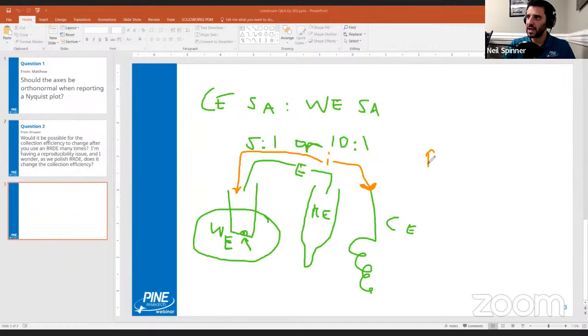So typically that's platinum, it's graphite. Sometimes if you're doing other kinds of systems, it'll be like a mesh, some people have like a nickel mesh or things like this, but basically just something that is a big surface area, large. The exact shape and size doesn't always matter, and in most experiments, it doesn't usually matter. There are some cases where people prefer to not use platinum.